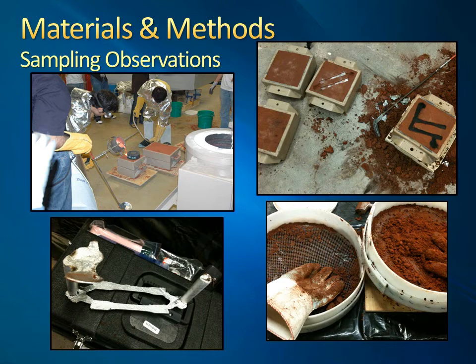In these photos here, the one in the upper left-hand side was not taken during the sampling analysis, but it's using the same materials and processes that we used. The other three photos are the molds that were created and the castings. You can see the spread of the green sand all over the place, and the sieves, and how much it actually does spread the green sand around.